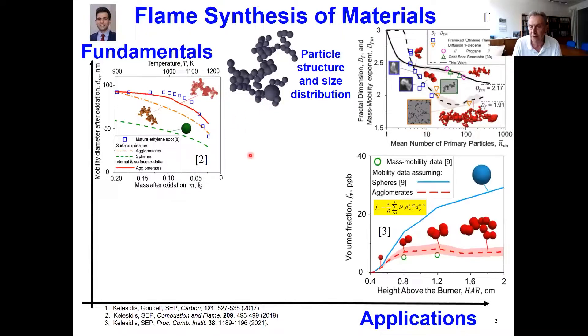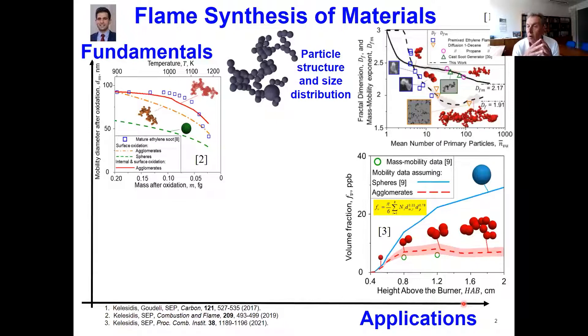Finally on the fundamentals, this year we were able to close the mass balance during soot oxidation. People over the years — even in papers from last year — are still off by a factor of four or five. However, by accounting for the structure and size distribution of soot, we distinguish between spherical and agglomerate particles and come extremely close to the data, plotting the volume fraction of soot as a function of height above the burner.